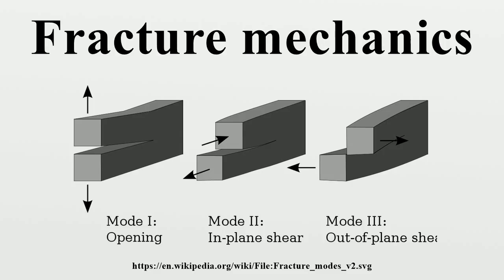Linear elastic fracture mechanics. Griffith's criterion. Fracture mechanics was developed during World War I by English aeronautical engineer A. A. Griffith, to explain the failure of brittle materials. Griffith's work was motivated by two contradictory facts. The stress needed to fracture bulk glass is around 100 megapascals. The theoretical stress needed for breaking atomic bonds is approximately 10,000 megapascals. A theory was needed to reconcile these conflicting observations.